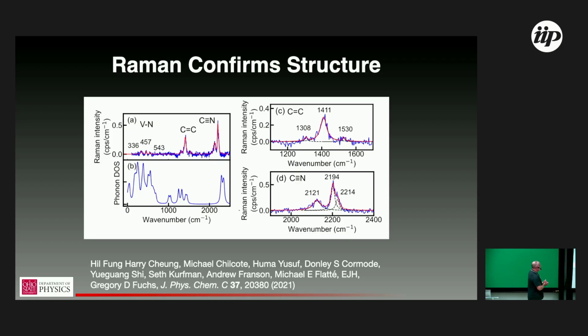We can also see evidence of this in Raman measurements. So these are measurements coming out of Greg Fuchs' lab, and you can see again the carbon double bond and the carbon nitrogen bond on the end both have identified Raman modes, which again the DFT model that we now have allows us to calculate and compares, I think, pretty well.